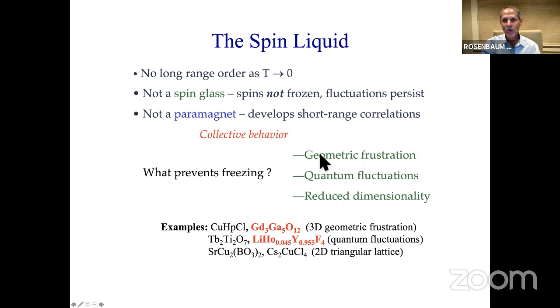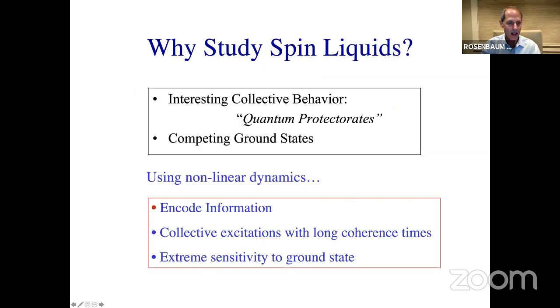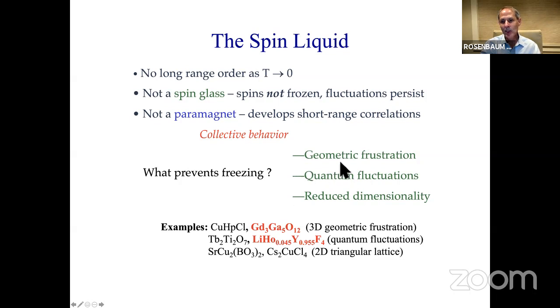Of course, the notion of spin liquids has been studied. There are many lower dimensional systems which show really profound effects. You can get the freezing prevented by the quantum fluctuations, which is what I'm going to talk about today in terms of lithium holmium yttrium tetrafluoride with 4% of the sites occupied. But you also can have geometric frustration and, of course, amplification of fluctuations with reduced dimensionality. We've done some work on gadolinium gallium garnet, which shows similar effects, but I won't show them here today.